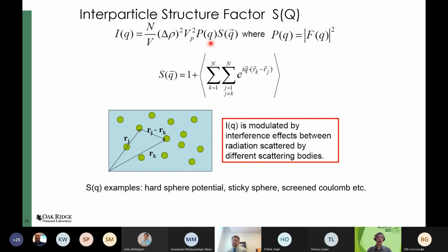This approach of a form factor times a structure factor works well in dilute solutions again, or somewhat more concentrated solutions. It depends though on the form factor and the orientation of the form factor not depending on the interaction. So there are some assumptions built in there. So this does not always work. It works for solution scattering typically, but one has to take this with a somewhat cautious approach.